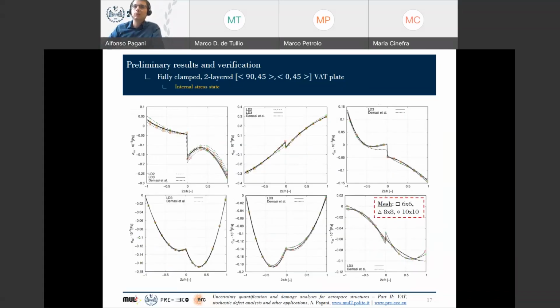In this slide, you see what we call the stress state, the stress distribution within the thickness of the plate. So you see that in general, for these structures, as Professor Petrolo says, you have 3D stress states. So you cannot neglect any stress contribution, but you should take into account all of them for doing consideration on failure. And usually the stress state is complicated. And in variable stiffness composites, it's even more complicated because the property of the material is changing not only in the thickness direction, but also pointwise in the in-plane direction. So this is the nominal stress state of our variable angle tow composites.